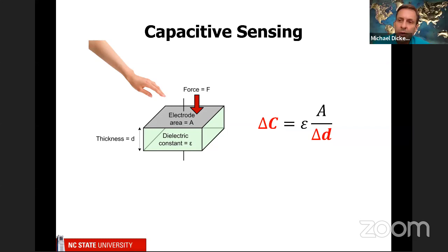Okay, so in the prior work, we basically used the kind of squishy nature of liquid metal to change resistance. Now here, I'm going to switch gears a bit and talk about changing capacitance. And there's lots of examples in the literature of people that have made soft capacitors that look just like this. And they measure capacitance by touching, by looking at the change in distance. The distance D is the height or the thickness of this dielectric layer. And so if you decrease D by squishing it, you make the capacitance bigger. So this is a way to measure touch.